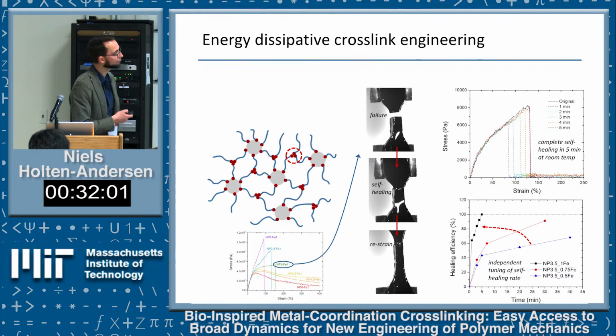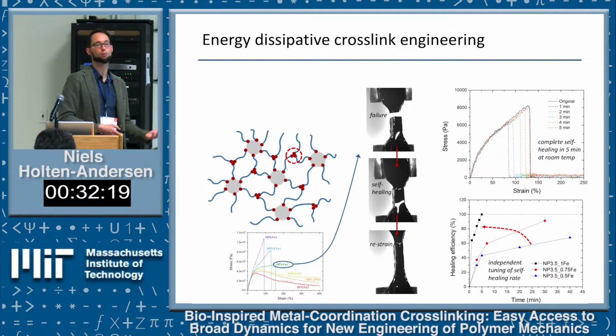but we change the amount of these short-lived bonds we have in there. This is a way of measuring the healing efficiency, how good the material is at recovering as a function of how long you give it time to recover. If you don't have a lot of metal ions in there, it never recovers, but the more metal ions you add, the quicker it becomes at recovering. So we can engineer the load bearing as well as the self-healing, which is otherwise really difficult to do with classical material design approaches.